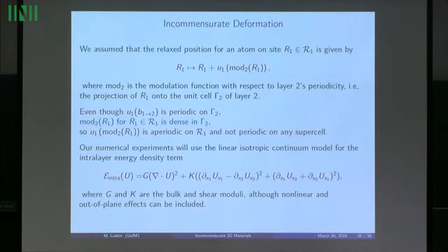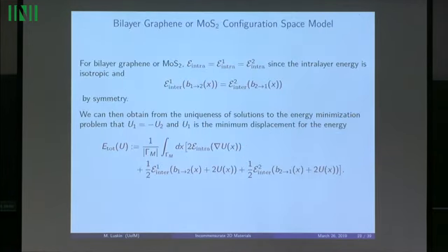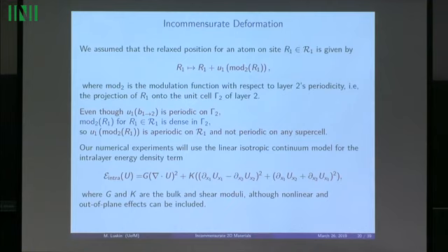All right, and so again, let me emphasize that we ended up with a problem on a periodic domain. But once we solve that problem, then we can reconstruct the atomistic positions from this relationship. So we can map cap U1 back to little u1. This is our formula to reconstruct the actual atomistic positions.